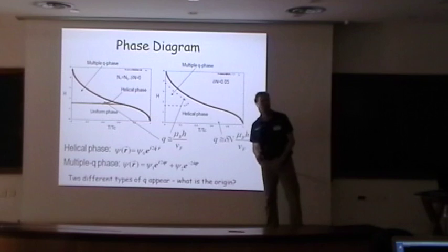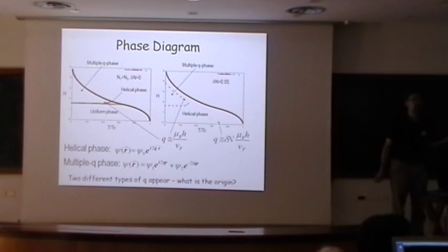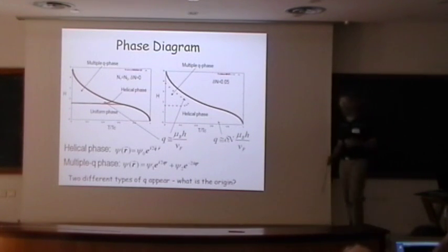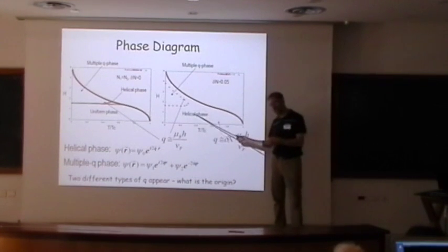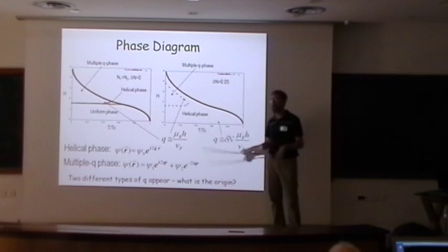Well, at least I've seen data from scanning SQUID microscopy. Basically you go around over the surface of the sample and you find some pieces of it are ferromagnetic, some pieces of it are diamagnetic. So it does appear that it is coexisting in the sense that it's lumpy, but it's not in the same place. Okay, so then that could be another reason. So then you could apply fields to these materials and look for these kinds of phases, because the helical phase should still appear.